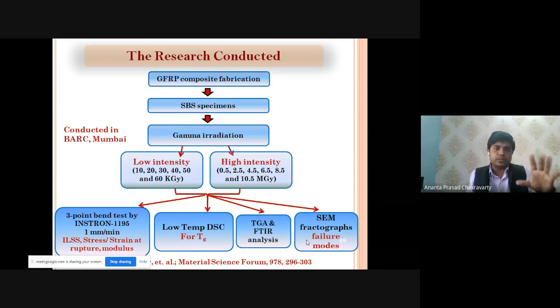Hence this was published in a very reputed journal, Composites Communications, in 2020. Now these glass fiber reinforced composites can be used as electrical and thermal insulators in superconducting materials. Keeping this in mind, I fabricated these materials first, then exposed them to gamma irradiation. I conducted this experiment at BARC, Bhabha Atomic Research Centre, Mumbai, for low intensity and high intensity.